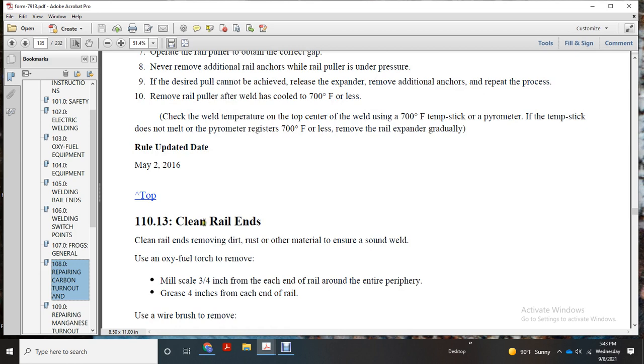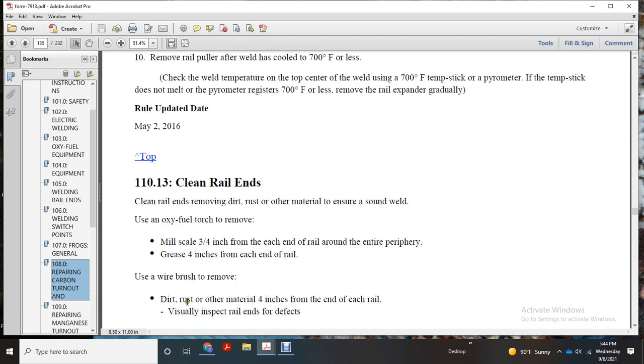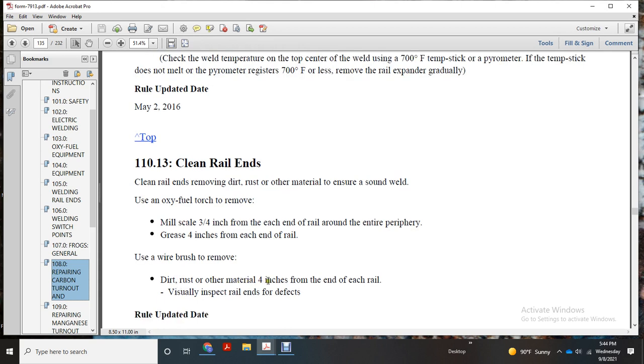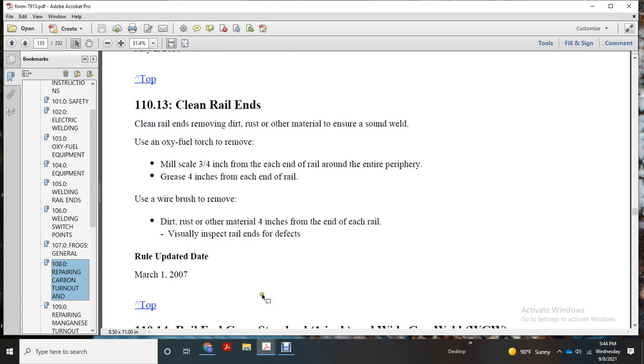Clean rail ends. Remove dirt and other material from the area of the thermite weld. Use the oxy-fuel torch to remove the metal scale 3/4 inch from the end of the rail around the entire periphery, and the grease 4 inches from the end of the rail. Use the wire brush to remove dirt and other material 4 inches from the end of each rail. Visually inspect the rail ends for defects.